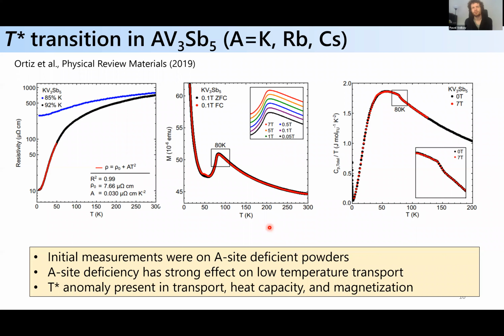Is there a strong magnetoresistance also for fields applied in plane? Because I believe this strong magnetoresistance you talked about is mostly for field along the C-axis, right? So is there any big effect if you apply an in-plane field? Yeah, it's weaker when you apply the in-plane field. There's still a little bit of MR, but it's much weaker than along C. Okay, thank you.